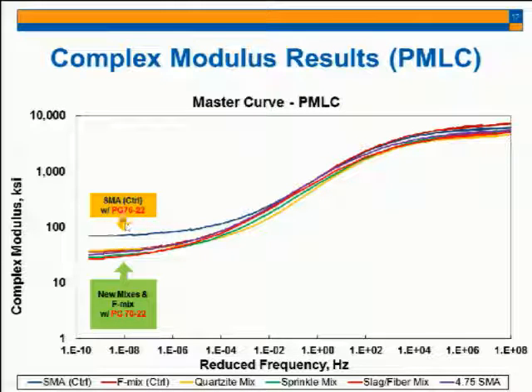So as you can see, we only use the PG 76-22 for the control SMA. For the other 5 mixtures, we use the PG 70-22. So you can see the modulus is almost identical in this area, but in the high temperature area, you can see the higher modulus in the control SMA mixture.